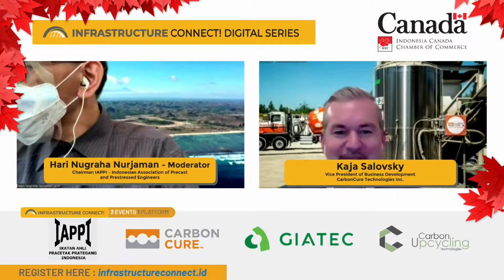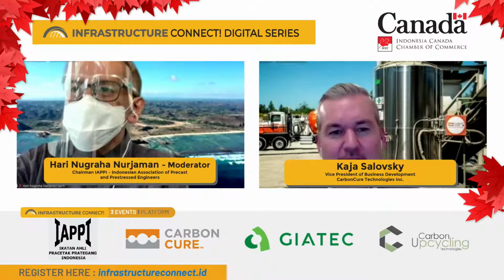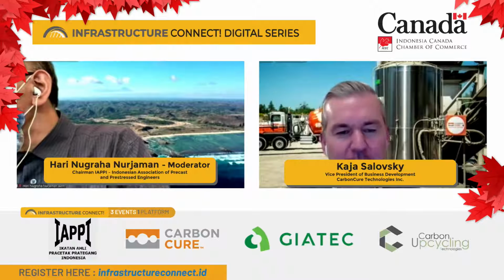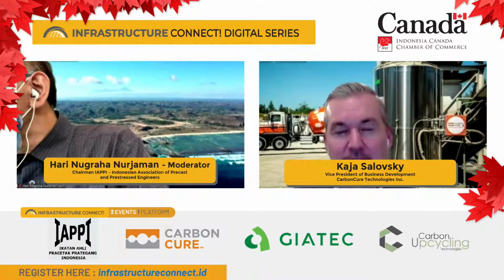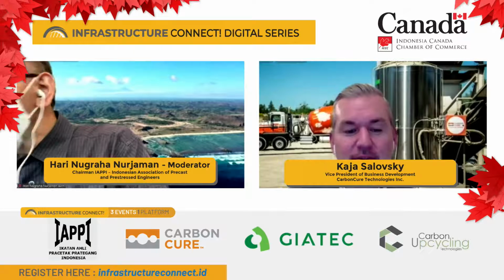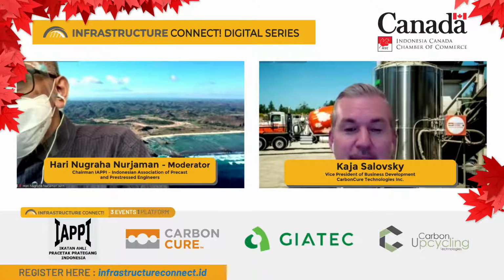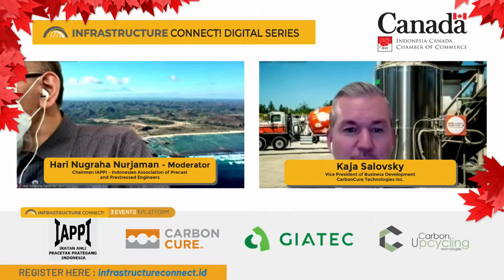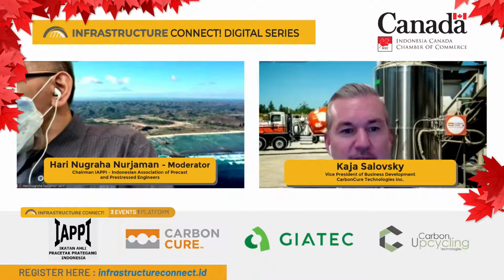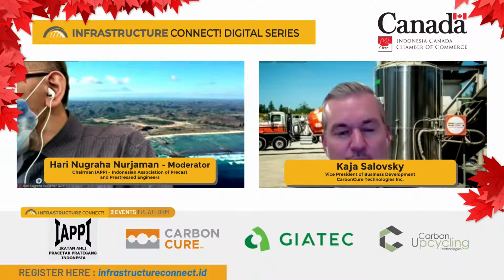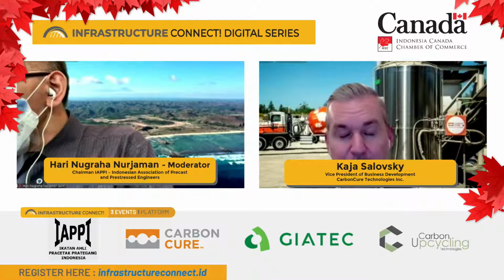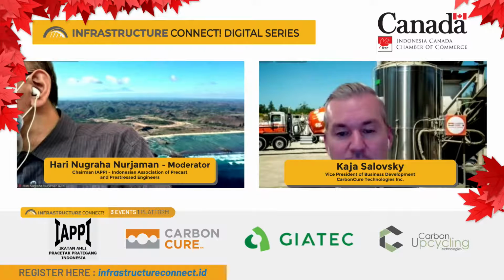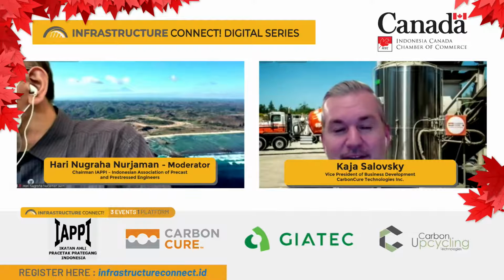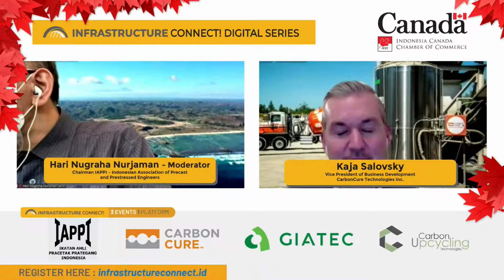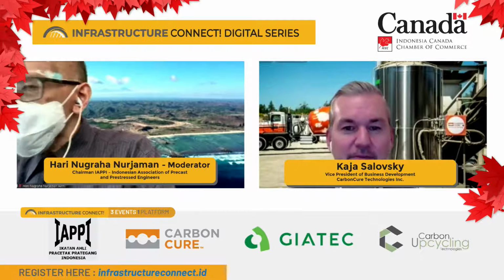It's a good question. The dosage of carbon has been developed through many years of research and over 4 years of commercial activity. During commissioning, when we start with a concrete producer, we evaluate the cement blend that they're using, and we dose somewhere between 0.2 and 0.35% by weight of cement. So if we think of a cubic meter of concrete, we're able to sequester somewhere between 700 grams and 1 kilogram per cubic meter. When we've tested our technology in a vacuum, we have found it to be approximately 92% efficient, meaning that approximately 8% of the carbon is lost to the atmosphere, but 92% of it is mineralized permanently in the matrix of concrete.